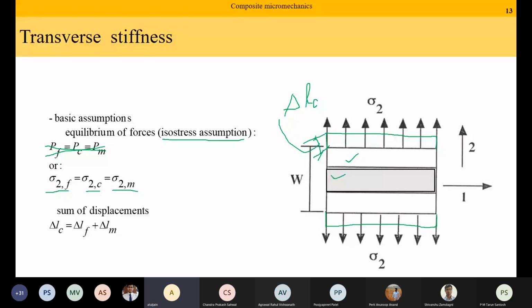We cannot make an isostrain assumption in the two direction because as I travel in the two direction, which is this direction, the fiber geometry is changing. Here there is no fiber. Here there is fiber, and here again there is no fiber. When the geometry of the fiber changes in a particular direction, isostrain is no longer valid. So we are making what is known as the isostress assumption. Isostress says that the stress in the fiber is the same as the stress in the matrix is the same as the stress in the composite. Okay, clear?